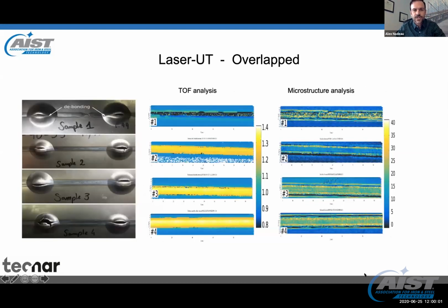First thing we did is we looked at 4 different welding parameters, from absolutely sure that it's good to absolutely sure that it's not good. They were bulge tested, and only sample 1 actually failed completely. The other 3 were good. And there's 2 different readings of UT in overlap mode presented here on the right. One is basically just time of flight that measures the thickness of the weld. And on the right side, it's the microstructure. We can relate that to grain size, recrystallization process due to the amount of heat.